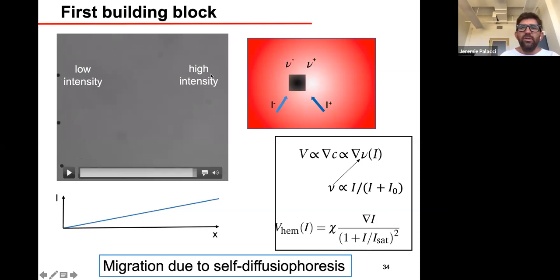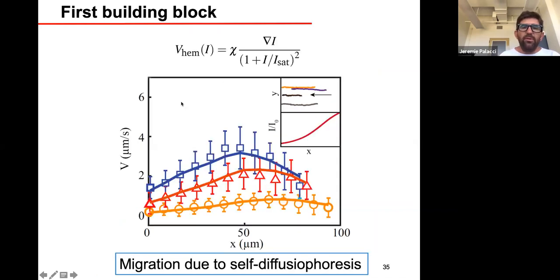So I won't get into the details, but I want to show you that this picture is adequate. We repeated experiments where we made different gradients of light. There are only two parameters in this picture, the saturation light and the mobility, if you'd like. And we can predict the speed of the hematite as a function of the spatial gradient of light we impose, with only two parameters.